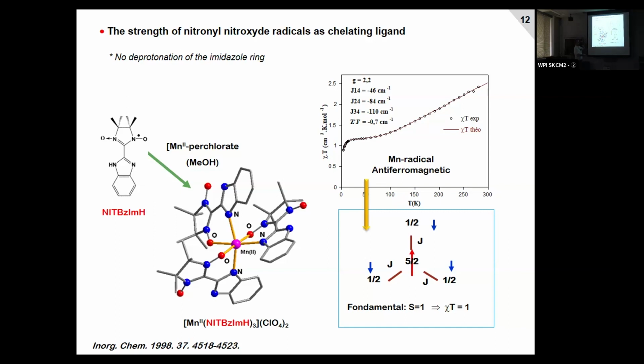Then when you cool, chi-T decreases. So we have confirmation that we have anti-ferromagnetic interaction, and you have here a plateau. Why do we have this plateau? Because the 5 half of the manganese 2 plus and the 3 spin halves of the radicals are coupled, so 3 spin halves minus 5 halves for the manganese. So the resultant is spin 1. For spin 1, the chi-T product is 1. So this plateau is due to the fact that the 3 radicals are anti-ferromagnetically coupled with the manganese.